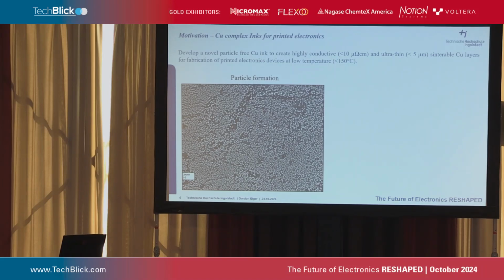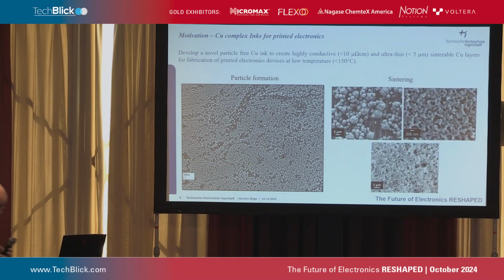You start with the metal salt. The salt has to decompose, release the copper. Then the copper forms particles, and you have to control the particle size. In principle, you would like to form as much atomic copper out of the salt as possible to have a huge amount of nucleation so that you form very many very small particles. However, that's a problem with outgassing. You can't do that so quickly because you have a lot of binder chemistry inside. So when you do it one way, you obtain large particles and small particles. You obtain too many big particles. You have to adjust the process so that you obtain very small particles, which are then later on sintered together.